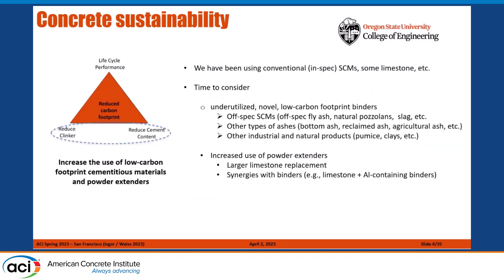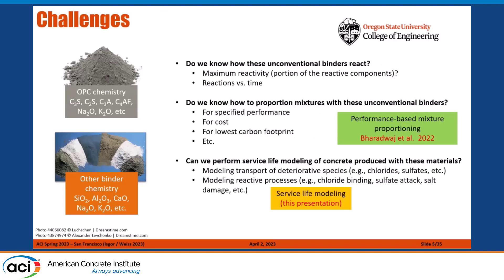The challenge we have is that the industry is going toward using very different mixtures, especially with performance-based approaches where we can be very creative. We all know conventional supplementary cementitious materials like fly ash and slag, but the industry is going towards underutilized SCMs — off-spec ashes, coal ashes, bottom ashes, reclaim ashes, agricultural ashes — and other industrial and natural byproducts like pumice and natural clays. We're also using limestone more prominently, extending its use and leveraging synergistic effects with certain SCMs. The systems we're envisioning for concrete are very different from what we have been doing.